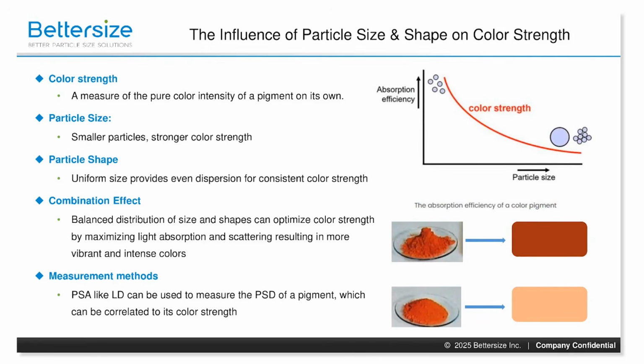Moving on to the size and shape effects on the optical properties. Two phenomena govern both hiding power and the color strength of inks, paints, and coatings: light absorption and light scattering of the pigment particles that are within the material. Color strength refers to the intensity of color a pigment can impart to a material, which is directly related to the size of its particles. Well-dispersed fine particles provide better color consistency and hiding power, resulting in vibrant color appearance, compared to larger, poorly dispersed particles, which tend to scatter light less effectively, resulting in a weaker color strength, leading to a more muted or dull appearance.